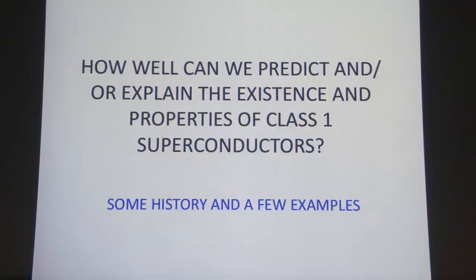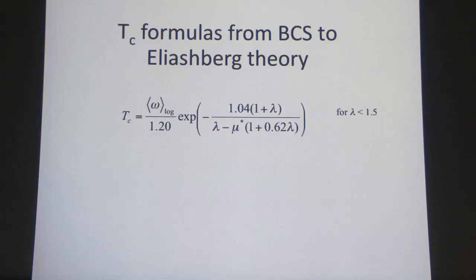Now, if you understand class 1, can you explain it from first principles or even predict them? And I'm happy to say that we're able to predict many of the class 1 superconductors. And we just have to know essentially one thing. This is a formula for the temperature for a superconducting transition. And the important thing to realize is that this lambda is the strength of the electrons coupling to the lattice. That's what's forming the pairs. This is the repulsive Coulomb interaction. You can forget about all the others. And this is the frequency that the lattice vibrates. So if I know the frequency the lattice vibrates and I know how strongly the electron couples to the lattice, I can give you the transition temperature because we can calculate this.